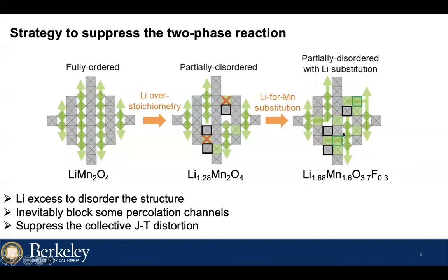In this work, we propose two strategies to suppress this two-phase reaction. The first one is lithium over-stoichiometry, which means putting more lithium into the structure. In this strategy, the cations will disorder, because if you look at this formula, that's actually the transition state between spinel and disordered rock salt. Although this disordering will block some lithium percolation network, like this lithium here, it will also break the collective Jahn-Teller behavior and could even make it a solid solution reaction instead of a two-phase reaction.